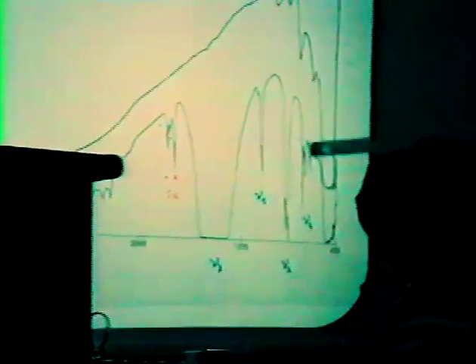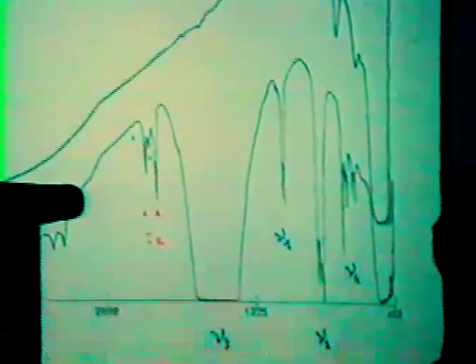Here I will show you the spectrum of the polymorph, almost pure 1B polymorph corresponding to the monoclinic structure. As it is a lower symmetry, you can see that the carbonate modes are split in several components, and you see here very sharp components.